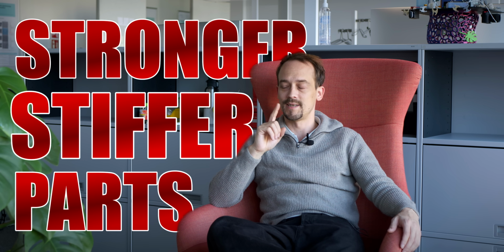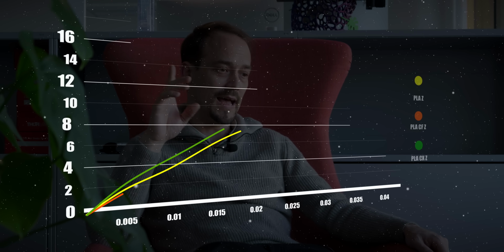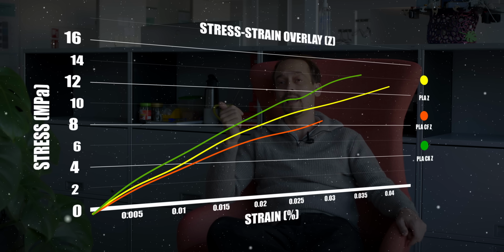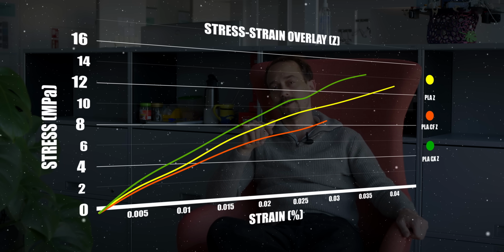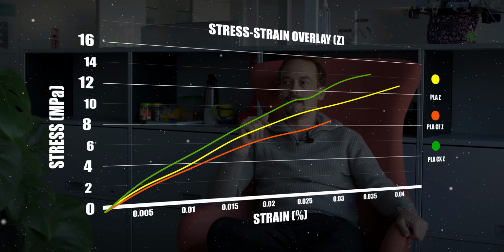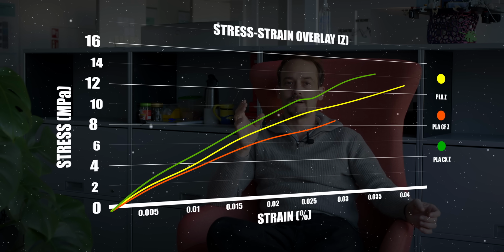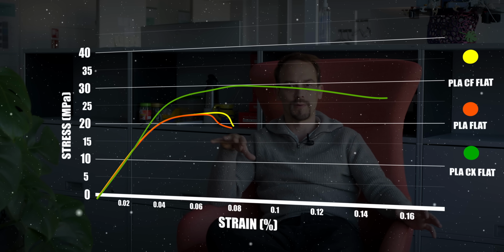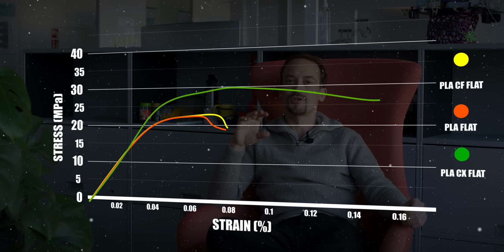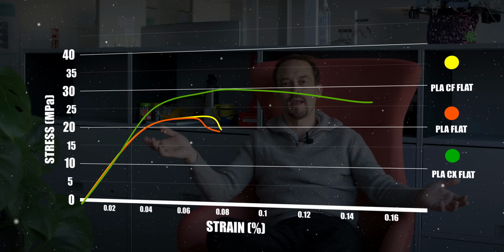So I would like to reveal the first thing of their claims, that was stronger, stiffer parts. So let's concentrate on the stiffness a little bit. We did our 3-point bending test again and compared to normal PLA and PLACF from our last video. And yes, it actually works. The parts are way stiffer. It's about 15 to 20% difference to the carbon fiber PLA and the pure PLA. So it actually did something.